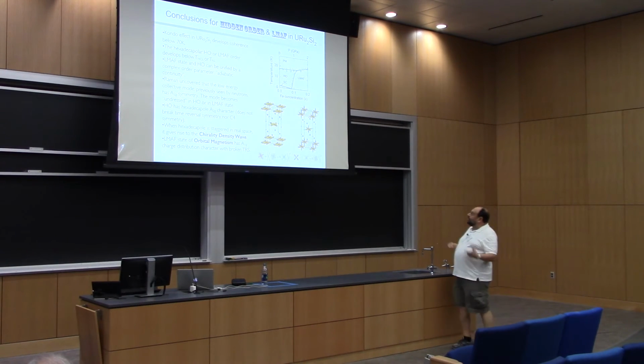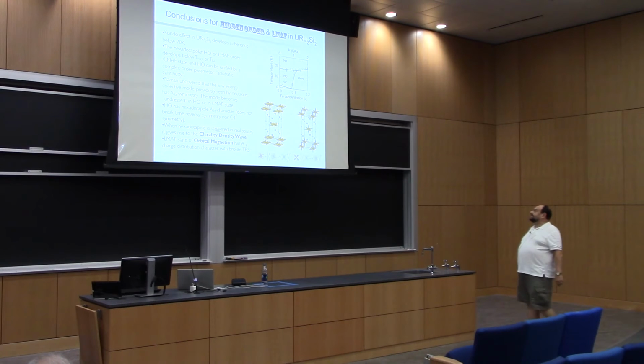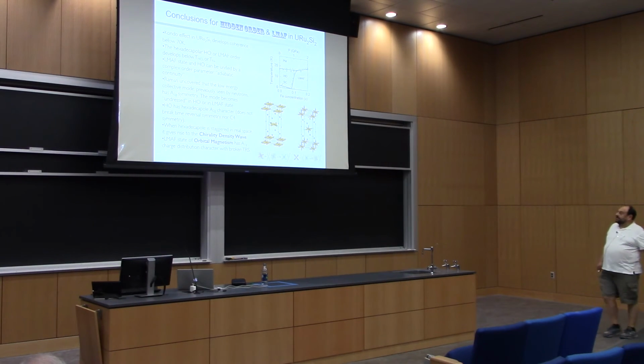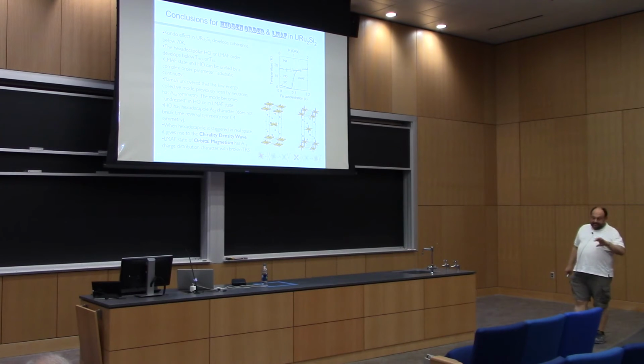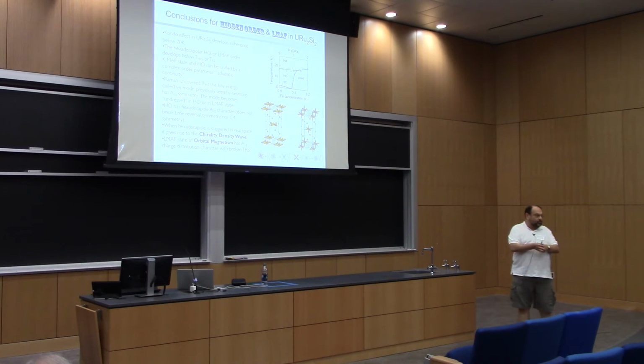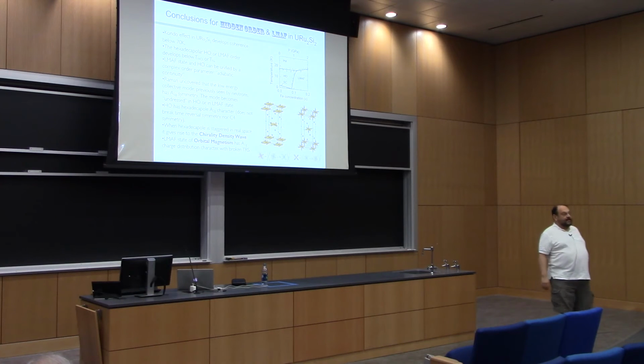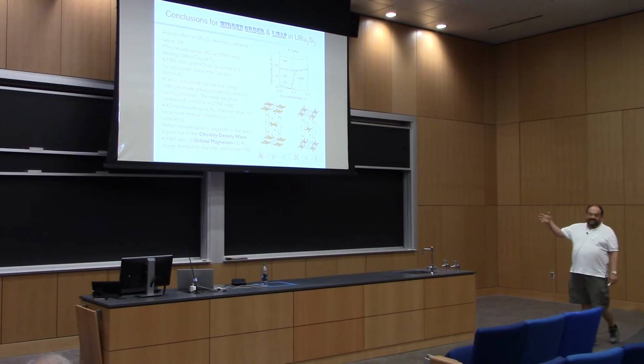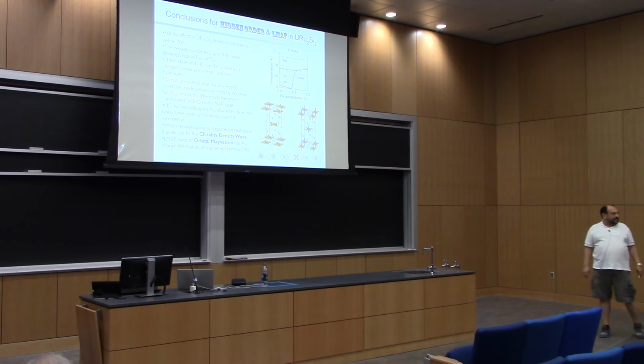So what we conclude from this spectroscopic study is that the pure hidden order state is essentially a chiral density wave, with no modulation of charge. There is a slight modulation of charge distribution due to the rotation of that chirality. And it's really accessible only by optics type spectroscopies. The true order parameter is staggered, and therefore one has to look for the Bragg peak. So seeing that Bragg peak would be the complete victory, not just seeing the collective mode.